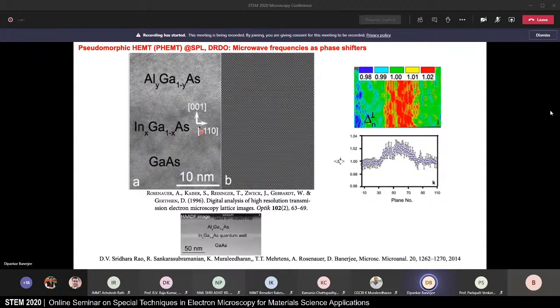How do we measure strain at these localized situations? Well, one technique is to look at these high resolution micrographs, look at the positions of the atoms or the interference patterns that lead to the atom positions, compare it to the positions of the atoms at some base through very careful digital analysis of these high resolution transmission electron micrographs. You can then define the displacement of atoms in this indium gallium arsenide layer in this example in relation to the atomic positions in the gallium arsenide.